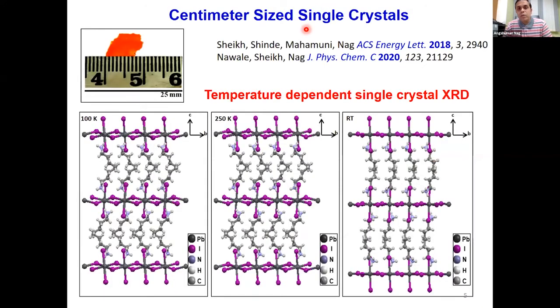So before going to the optical properties and discussion, let me convince you that the material that I'm talking about consists of large single crystals. They have lateral dimensions of about 1 centimeter and thickness of about 0.5 millimeter. You can take one of these single crystals and do all the optical properties and structural characterization on a single crystal. And these are just showing that we have all the structural details. These are single crystal XRD data at different temperatures. So we have complete knowledge of the structure of the material, because we are studying single crystals.